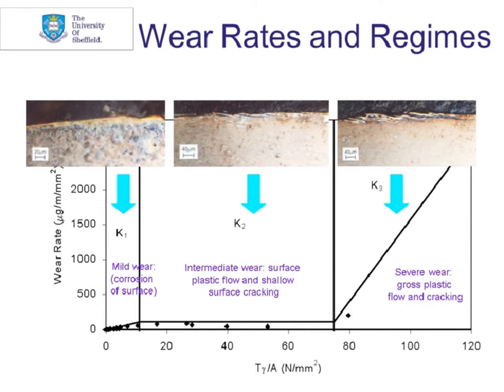And you can see here how the subsurface features within the wheel material change from a very thin layer of oxide, very low levels of deformation, through to the very severe end where you've got lots of material flaking away and quite high levels of deformation. So these wear coefficients you see defined there are the things that can be used alongside that mesh of contact conditions within the wheel-rail interface to predict how much material is removed and then assess how the profile evolves.